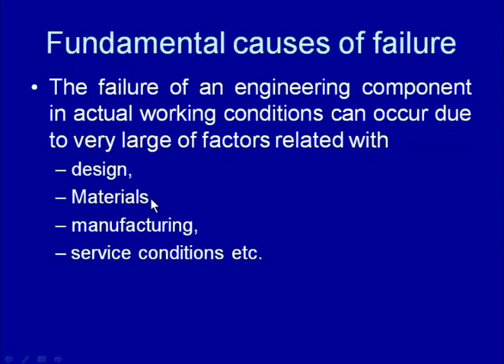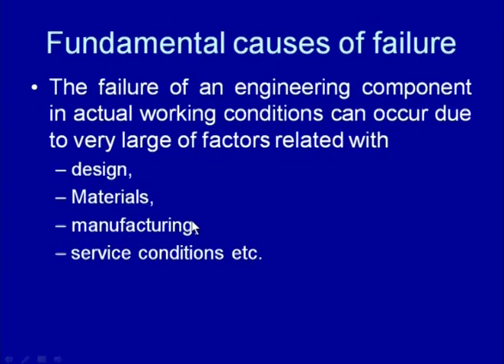Like there may be a deficiency in the design of the component itself, because of which it could not perform under the given load conditions, given service conditions, or there may be a deficiency related to the materials, like the material is not able to withstand the service conditions, and this can lead to premature failure of the component or the weld joint during service. Then the manufacturing process is not efficient or not as per the recommendation. For example, if it was recommended that for aluminum welding helium or argon should be used, but instead, carbon dioxide with some percentage of oxygen is being used, then that can lead to a number of discontinuities and defects in the weld joint.